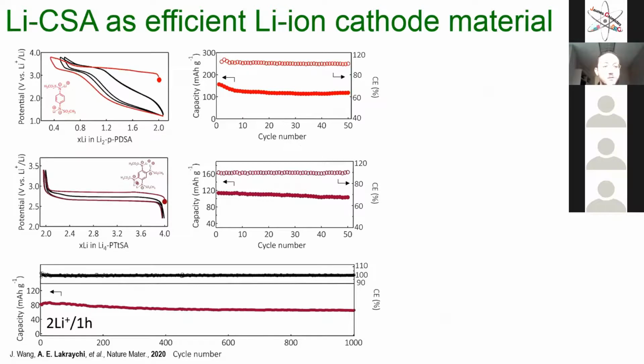In terms of battery performance, the reference molecule can react at a potential above 3 volt during the oxidation, but during the reduction, which is the discharge process, we have a kind of voltage hysteresis. For the moment, we don't know why we have this. It remains unsolved, but it's a good material and it shows a good stability during 50 cycles.